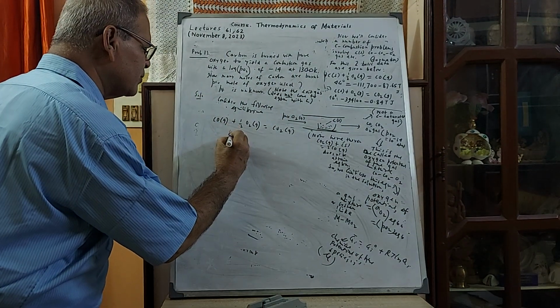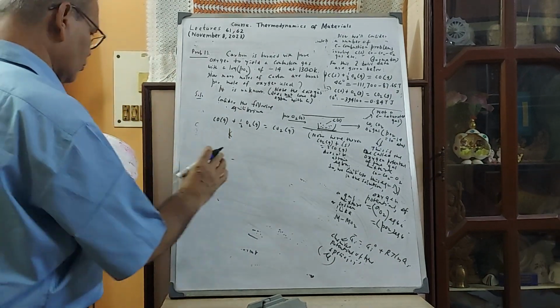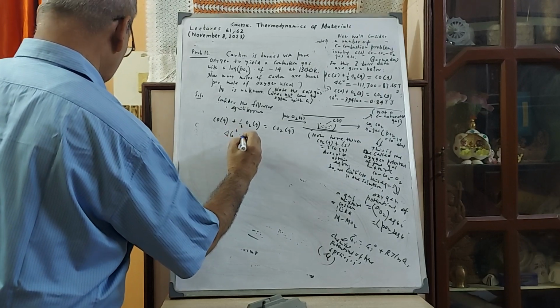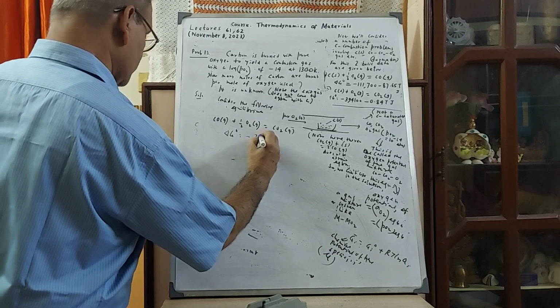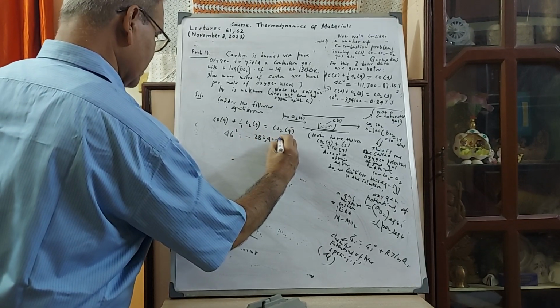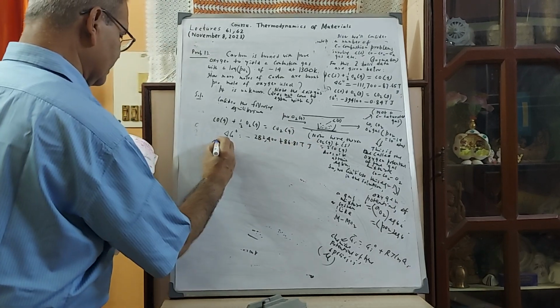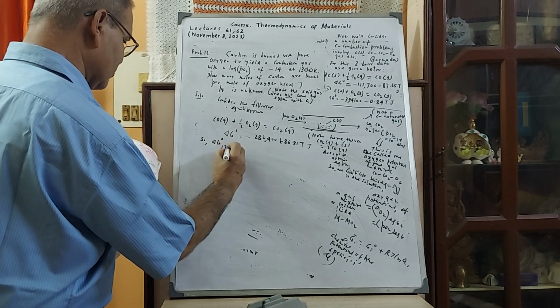So K. At what temperature? Here I will help you. Delta G0, since I am using the data, is minus 282,400 plus 86.81 T joule. So quickly, you should consider delta G0 at 1300.